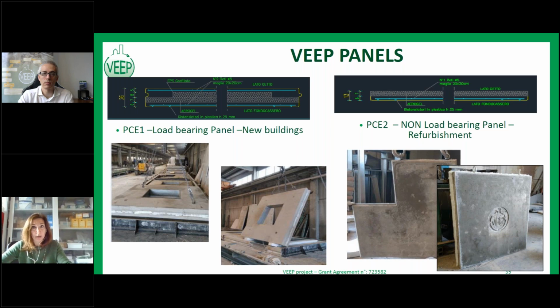it has like a lower thickness. It is in fact 13 centimeters. It still has 7 centimeters of aerogel and just 6 centimeters of concrete. This specific type of construction element has, again, a higher quantity of aggregates, recycled aggregates, and low weight concrete, recycled concrete. And it has a fire resistance of 90 minutes.